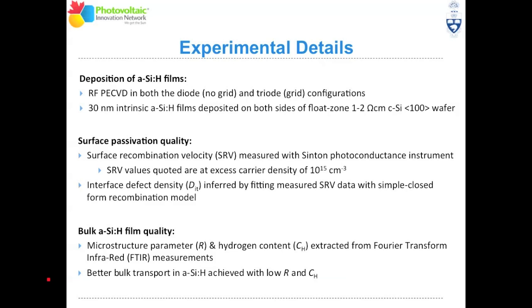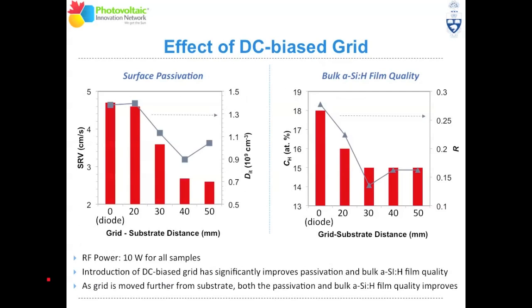So it's really important to have films that aren't really defective, so you don't get a lot of recombination in the amorphous silicon layers. And we were able to measure the bulk film quality by looking at the hydrogen content and the microstructure parameter of the amorphous silicon films, where lower hydrogen content and lower microstructure parameters point towards higher quality bulk properties.